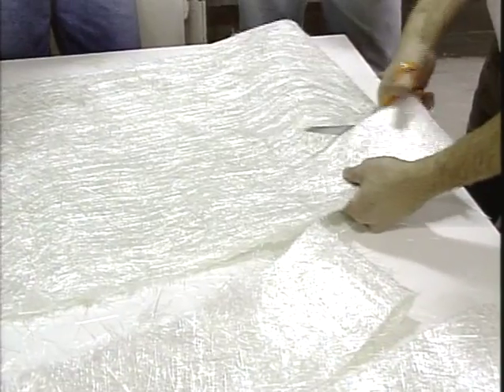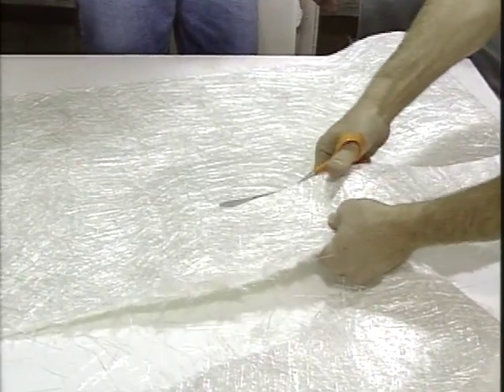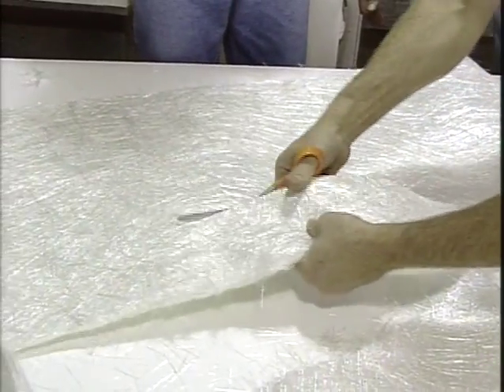The first layer of reinforcement is also very important. It must be applied without trapping any air pockets. If an air bubble exists in this layer, the gel coat is unsupported and will collapse when the mold is put into service. As a rule, neither mat nor woven fabric can be expected to lay around a 90-degree or smaller angle without developing air pockets.